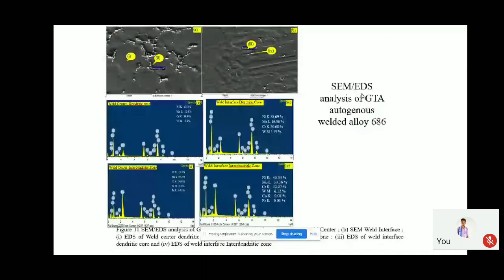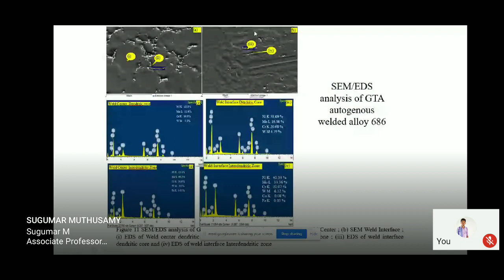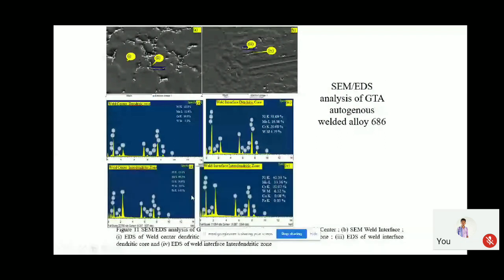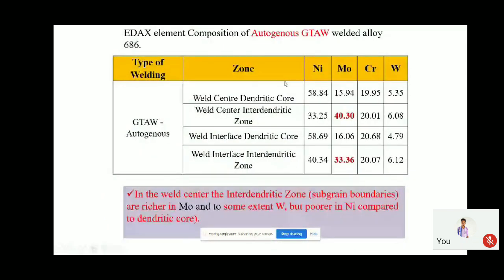So what is happening, sir? Actually, if you are not choosing the proper filler material, what will happen? You can see here the value of molybdenum. Right here it is 16%. Over here it is 33%. What is happening? These white color particles are called segregation. So the elements are segregated in one particular place. It is called the interdendritic zone. When you put it to real-time applications, the cracks will be initiated over the interdendritic region because of this segregation. If you see here, the molybdenum is 15 and here it is 40, here it is 16 and 33.